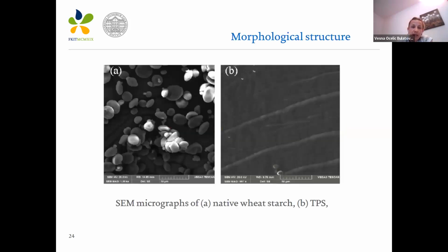On this slide, we can see the morphology, the SEM micrographs of native wheat starch in figure A. As we can see, the native wheat starch has a granular structure. These granules are spherical, oval, and of various sizes, and are prone to agglomeration. During the plastification, a transformation of granular morphology into a homogeneous polymeric film occurred. We can say that the thermoplastic starch was obtained.